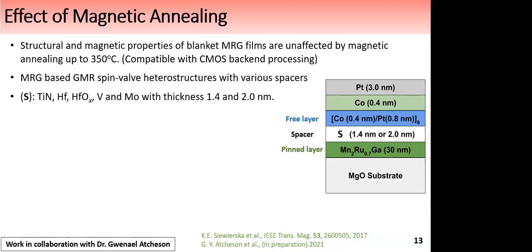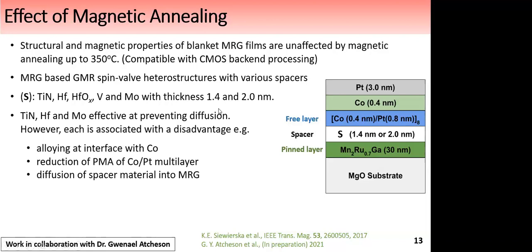The spacers chosen for this study were basically selected based on their performance as diffusion barriers and also their lattice parameter in order to match that of MRG. And they were deposited at 2 different thicknesses. What we find overall is that TiN, hafnium, and molybdenum are effective at preventing diffusion. However, each of these spacers is associated with a disadvantage. Those disadvantages include alloying at interfaces with cobalt, reduction of perpendicular magnetic anisotropy of the cobalt-platinum multilayer, and also diffusion of spacer material into MRG, which can affect the properties of MRG, such as compensation temperature or even spin polarization.